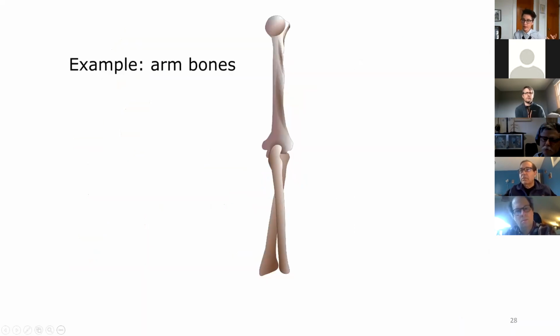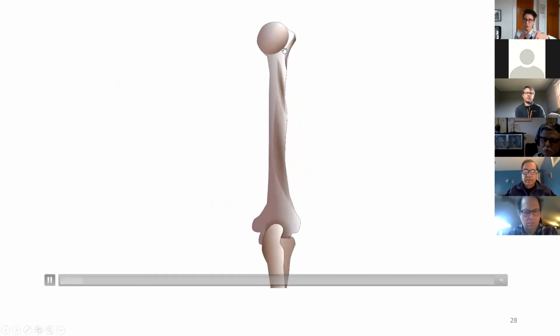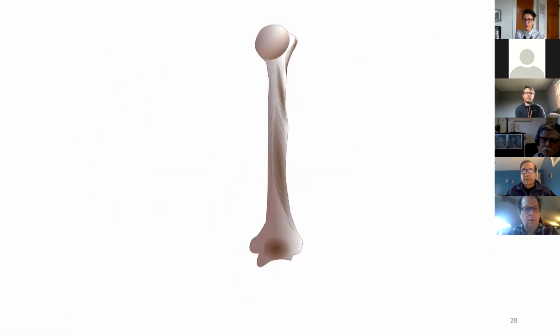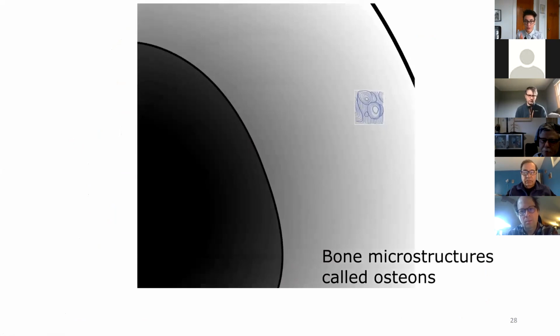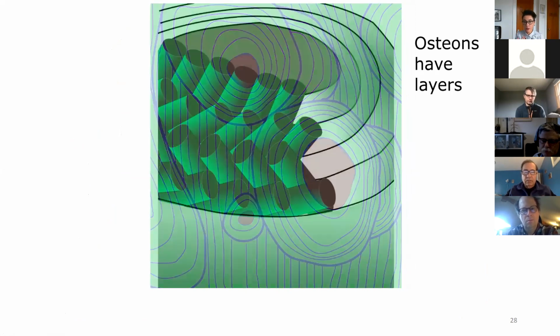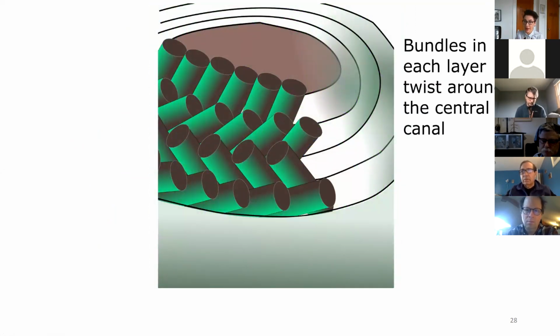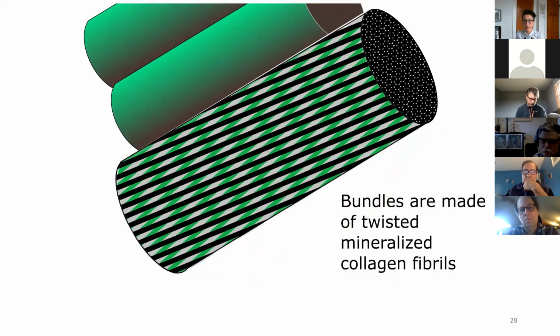So now if we connect the dots and all the information that we know from gross anatomy and histology and electron microscopy studies, an interesting picture will emerge. So at the level of gross anatomy, bones have a certain twisting pitch. The ridges are twisted. And then within every bone shaft, we have capillaries that propagate through the cortex following a very gentle 15 degrees twisting pitch. These are Haversian canals. Around each of them, we have an assembly of lamellae, and every lamellar structure is twisting around the central canal with a varying angle.